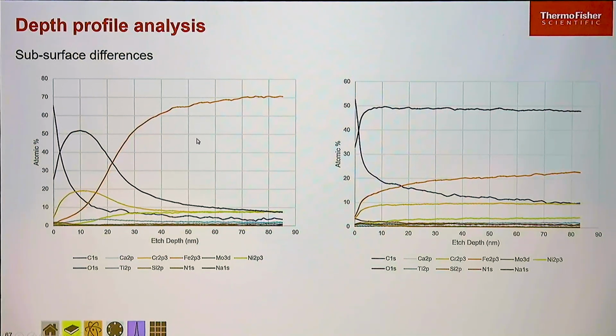Now, colleagues in the electron microscopy group had been looking at the same sample as well, and they wanted to look at this very thin layer. So everything's happening within the first 30 nanometers or so of the surface. And so the way they would look at that is put it into a FIB system, cut a cross-section, take it and have a look in the TEM and do it that way. And that's quite a time-consuming process. Whereas to do this took 20 minutes. And so we were able to get an answer considerably faster.